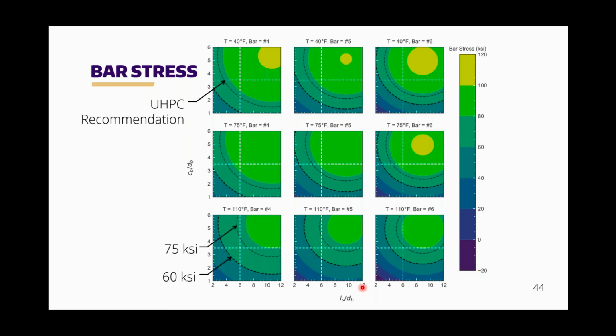As you increase the normalized splice length and as you increase the side cover, you see that you have a plateau which occurs in this upper right corner. In terms of variation versus temperature, you can see that the yellow dots get smaller and the blue circles get smaller as you go down. So that's just saying that as temperature increases, the bar stress decreases. That seems true as well. If you go from bar diameter now, you start seeing a lot less variation, which is exactly what we're talking about with this normalization.